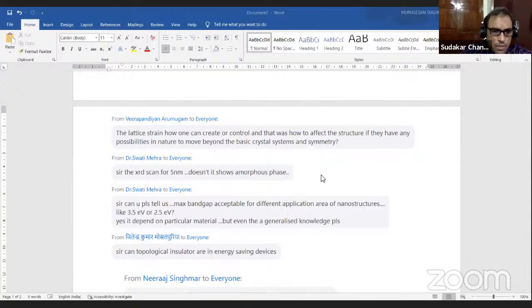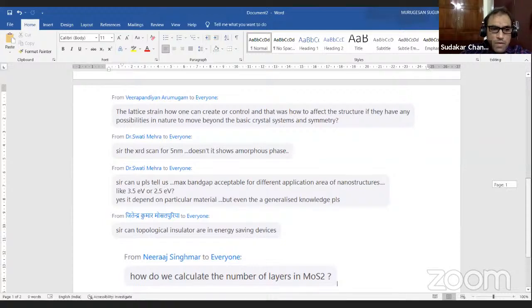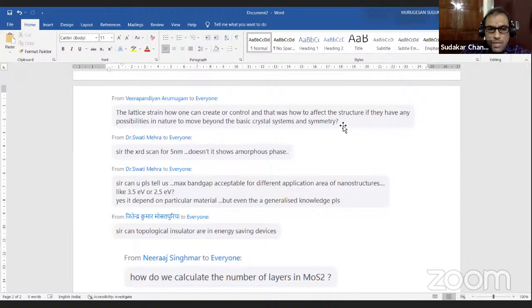Can you please tell us the maximum band gap acceptable for different application areas of nanostructures, like 3.5 eV? I didn't get what this question is. Different applications means what? For example, for the solar cell I discussed, you need 1.5 to 1.7 eV. That's where you get maximum efficiency. The Shockley-Queisser limit suggests that maximum efficiency can be obtained when you have a band gap of around 1.5 eV. We can use materials with a larger band gap, but then a lot of the energy that the photons bring from the sunlight gets wasted as thermal heat, and therefore it does not effectively convert solar energy into useful electrical energy.